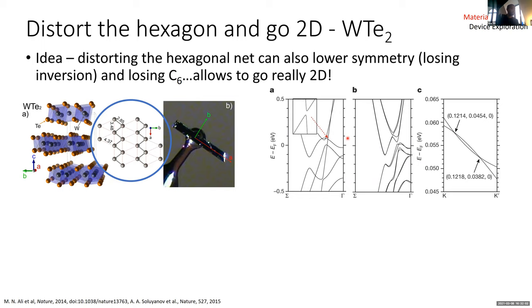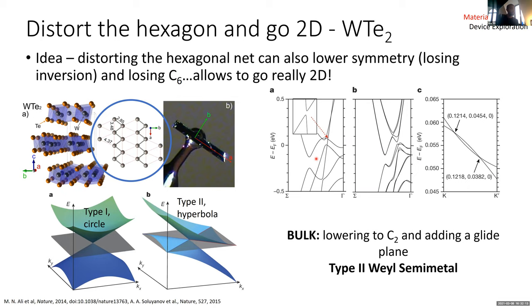And so there have been many interesting papers now delving into the nature of the electronic structure, but it basically manifested the first so-called type 2 Weyl semimetal, where in a type 1 that we talked about before, the Fermi surface cross-section cuts through either a circle or a point. In a type 2, because the Weyl point is coming from essentially tilted pockets, you end up cutting a hyperbola. So that's all well and good. And it manifested an interesting electronic structure topology like we hoped.